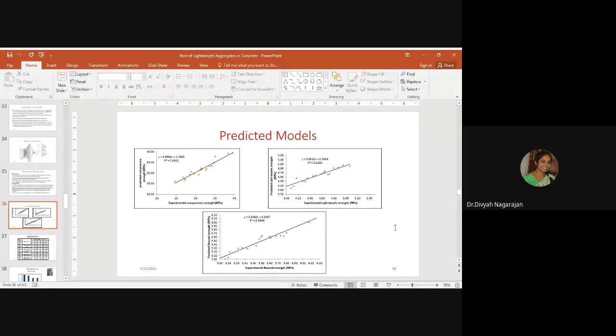Although many new techniques have come up recently, the ANN predicts in a better way when compared to other models. For the experimental compressive strength and the predicted compressive strength, the R-square value is around 0.93, whereas for split tensile strength and the predicted split tensile strength, the R-square value is 0.92. For flexural strength, the R-square value is around 0.94, which is the closest prediction.